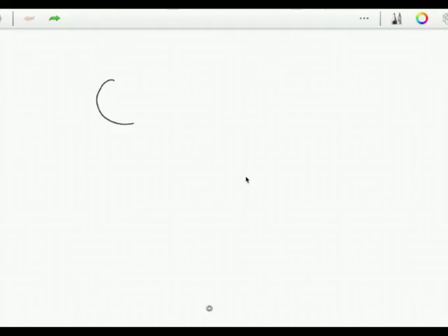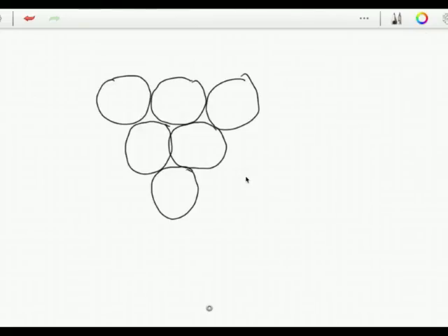So the close-packed plane of FCC looks something like this. So this might be the close-packed plane of austenite, where the atoms are touching along the 110 type directions. If I draw a lattice vector, that means a vector which takes you from a lattice point to another lattice point, then that is the lattice parameter divided by 2 into 110. And that takes me from a lattice point to a lattice point. So a dislocation with this Burgers vector would not change the structure.